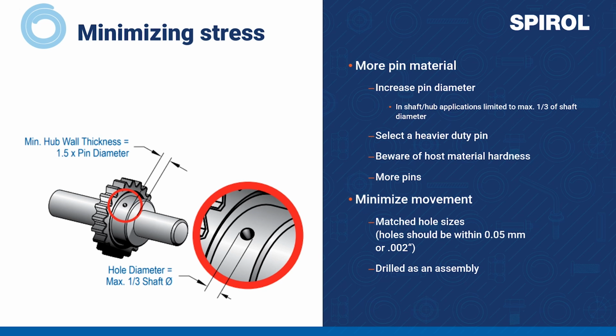Before making the move to a heavy duty pin, though, we need to make sure that the host material is sufficiently hard and strong to accommodate it. If we used heavy duty in aluminum, for example, the comparatively high stiffness of the pin would have essentially the same consequences as a solid pin, and the service life could actually be decreased. Generally speaking, it's better to go to a larger diameter standard duty pin before moving to a heavy duty pin, except in very specific applications.